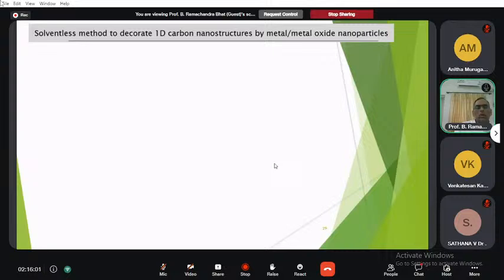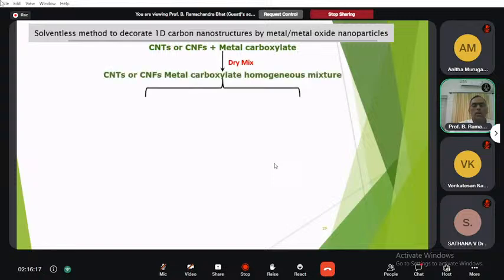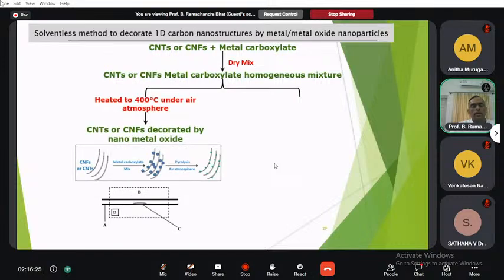So without using any solvent, and this is reported for the first time. CNT or CNF, anyone is taken and treated with the metal carboxylate. It's a dry mixture, and you mix it well, and a CNT or CNF metal carboxylate homogeneous mixture is formed, and then take this and heat to 400 degrees under air atmosphere. Then CNT or CNF will get decorated by the nano metal oxides.